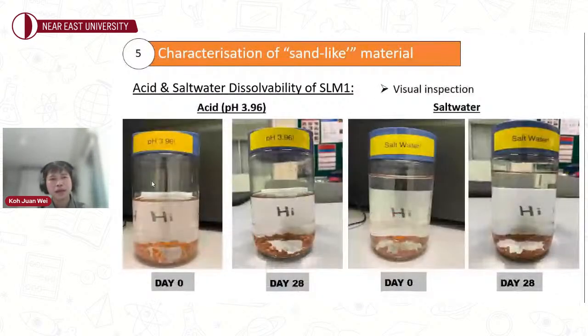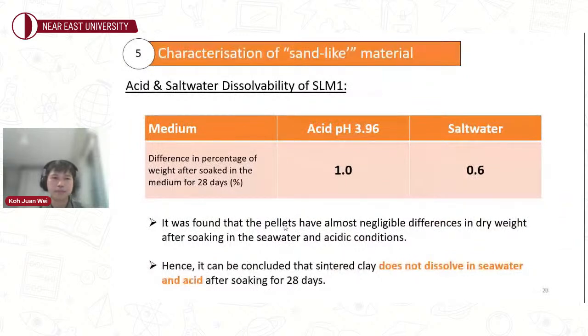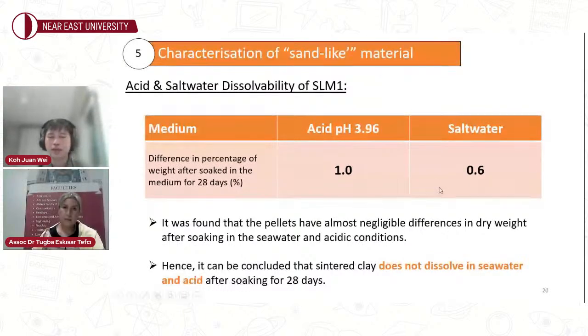So these four pictures show the real conditions when we soaked our product in acidic and salt water conditions. The left hand side is day zero, and after 28 days, the color of the solutions is very clear and there is no muddy condition. From this observation, we can say that our product is not dissolved at all. We also weighed the samples before and after soaking, and the difference in percentage is very small. In acidic conditions, it's about 1% difference in weight, whereas for salt conditions, it's only 0.6.